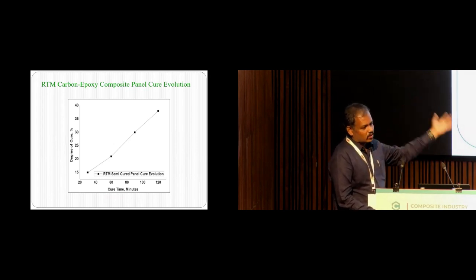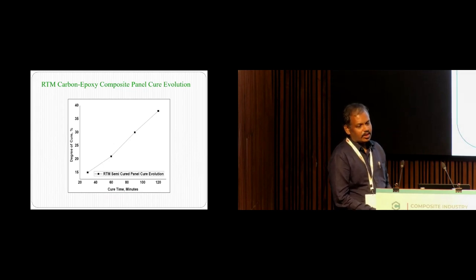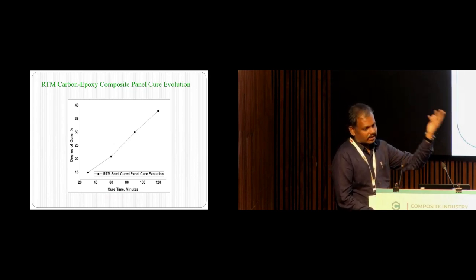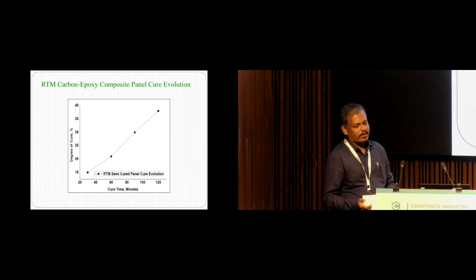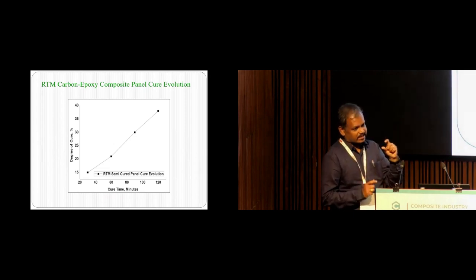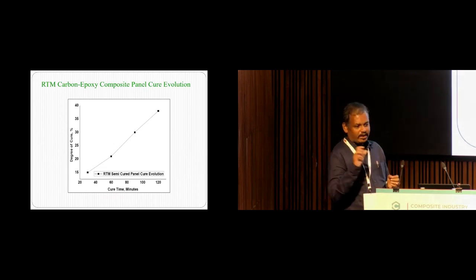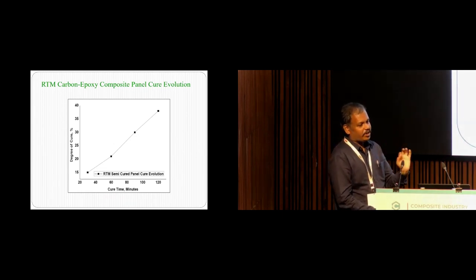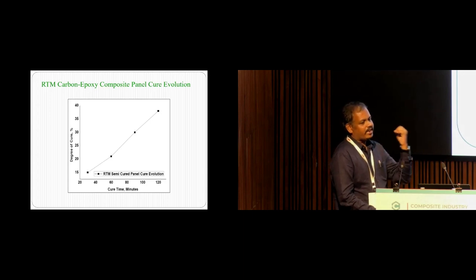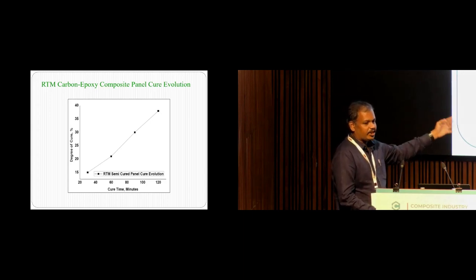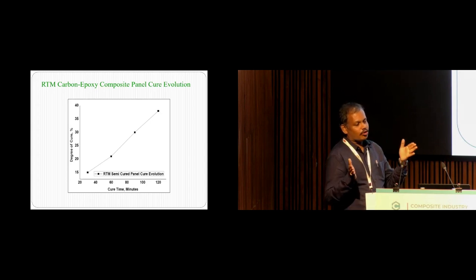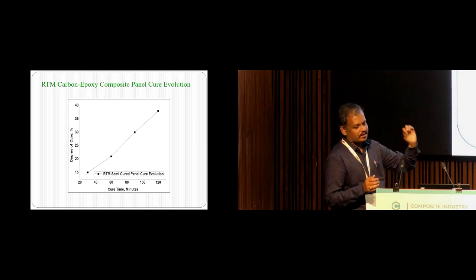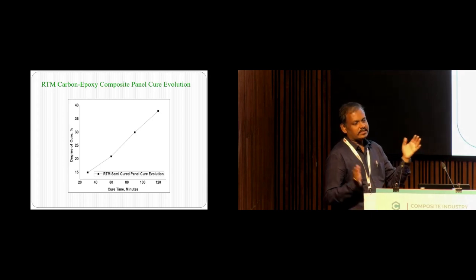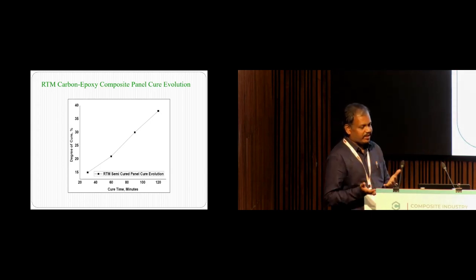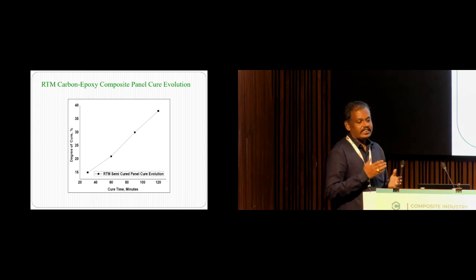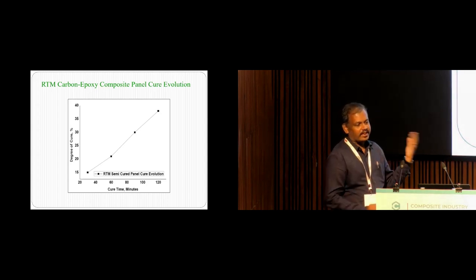So we have done a lot of experiments, and we compared the cure evaluation behavior of the resin as well as of the panel at different thicknesses we have evaluated. We have made a model such that it will predict if you increase by 5 to 10 degrees centigrade over the designed cure cycle, the cure differences between the laminate and the neat resin can be reduced, which means the composite panel will behave like the resin cure.